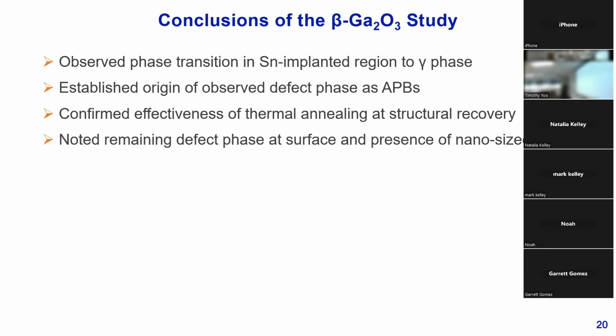And so to conclude for this gallium oxide study, we've used atomic resolution imaging to confirm the phase transition occurs, but actually to the gamma phase. We've also been able to establish the origin of the observed defect phase as being the antiphase boundaries. We were able to confirm that thermal annealing was really good at recovering the structure for the most part, but there were remnant defects to note particularly at the surface, as well as those nanovoids that are going to have consequences for things like carrier activation and carrier mobility.